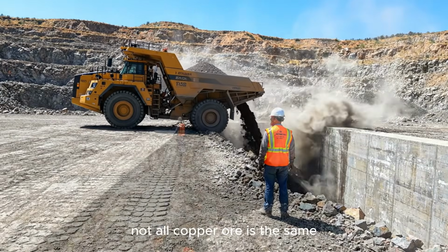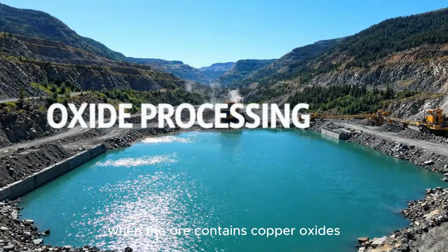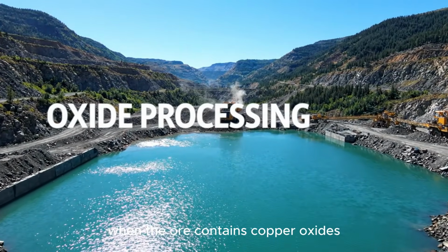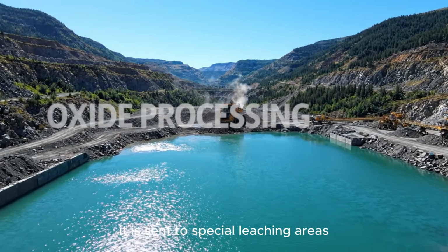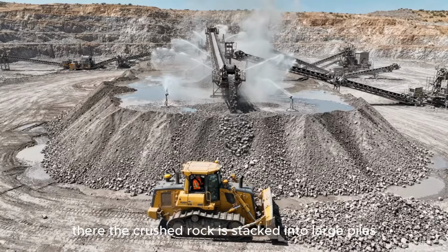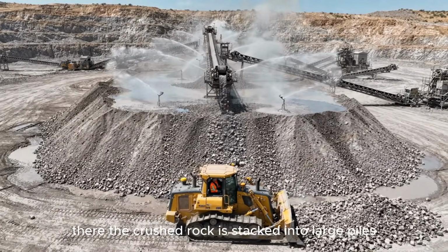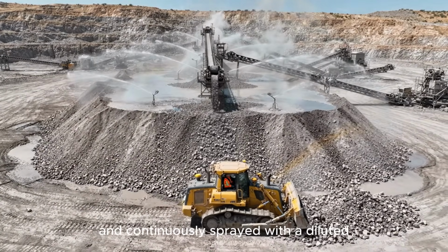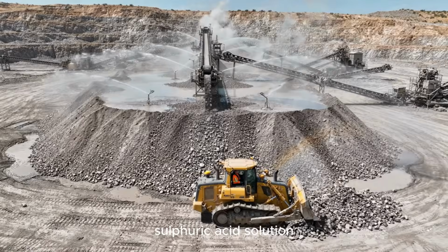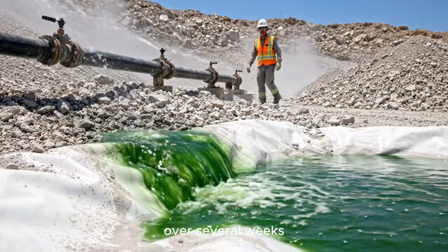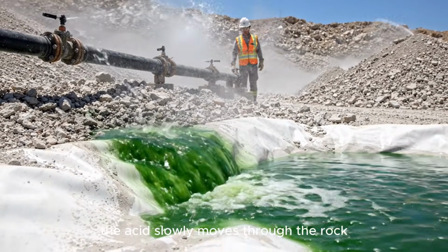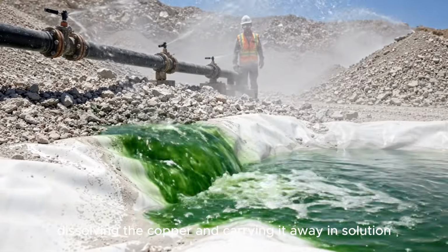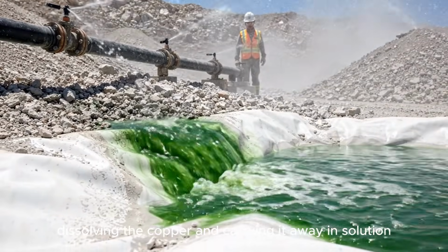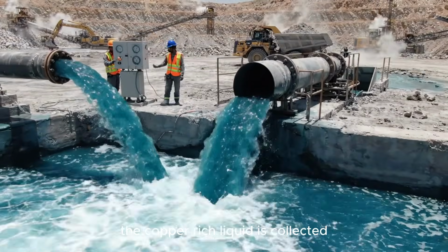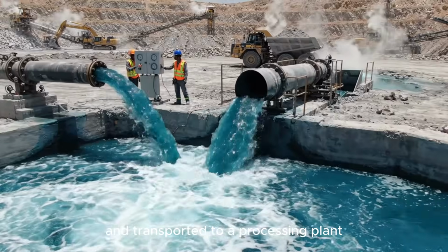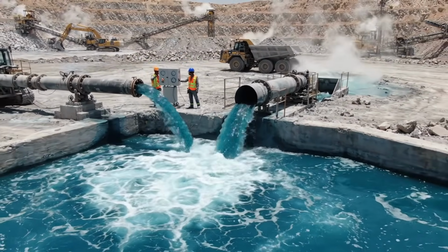Not all copper ore is the same. When the ore contains copper oxides, it is sent to special leaching areas. There, the crushed rock is stacked into large piles and continuously sprayed with a diluted sulfuric acid solution. Over several weeks, the acid slowly moves through the rock, dissolving the copper and carrying it away in solution. The copper-rich liquid is collected and transported to a processing plant.